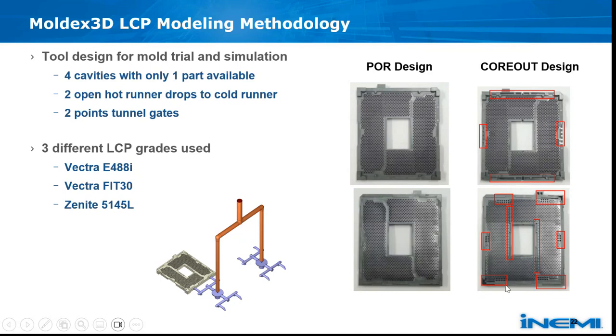So all the simulation models are generated based on the tool design for the mold trial. You can see there are 4 cavities in one mold with a runner system and 2 runner drops connected to a cold runner. But in the mold trial, only 1 cavity is available, and the 2-point tunnel gates are used for the cavity. And 3 distinct LCP materials are used for the validation. All the 3 materials are fiber reinforced plastics, so not only the temperature and the pressure, but also the fiber orientation information from the filling analysis is necessary to precisely predict the warpage of the molded circuit.